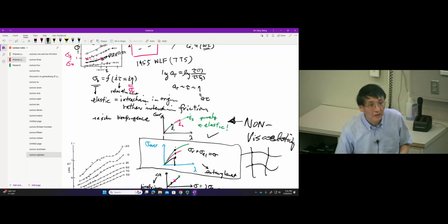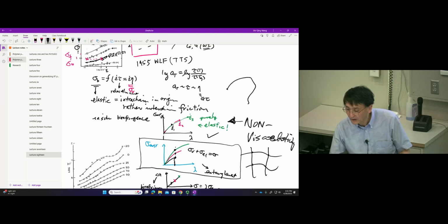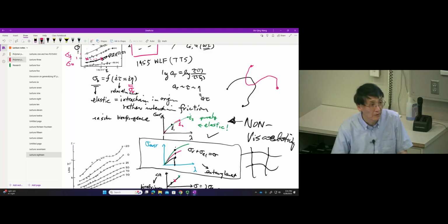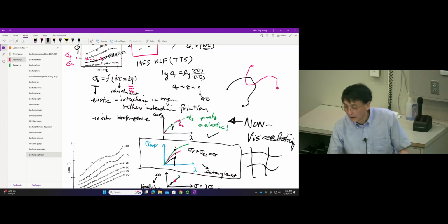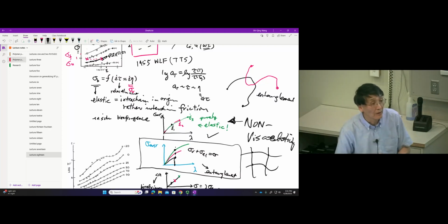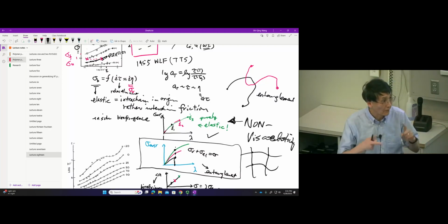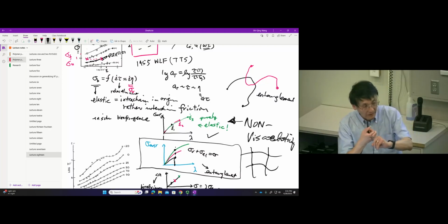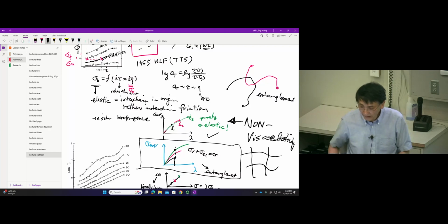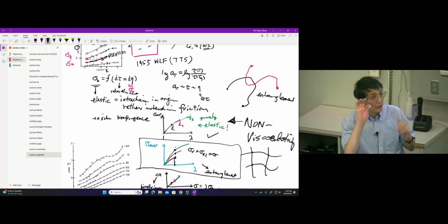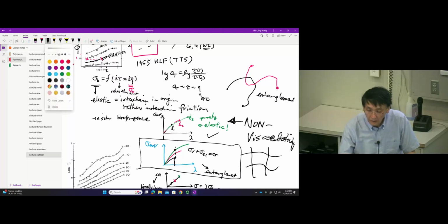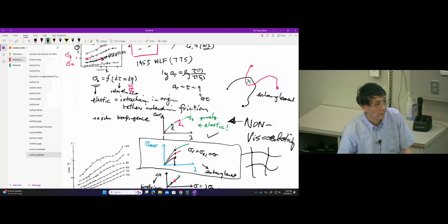And to be more explicit, it's conceivable that structure is this uncrossability producing entanglement. And the way you can call it embedded or trapped entanglement. Basically, especially the way you make your polymer is to start with the entangled melt and then cross-link a few places. Necessarily, you trap the entanglement, meaning trap the topological constraints between chains through uncrossability. So depending on how fast you're doing it, this red and black chains may or may not be engaged in producing this extra quote-unquote cross-linking point here, right? So that depends.